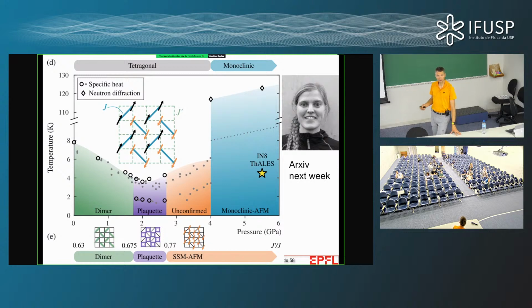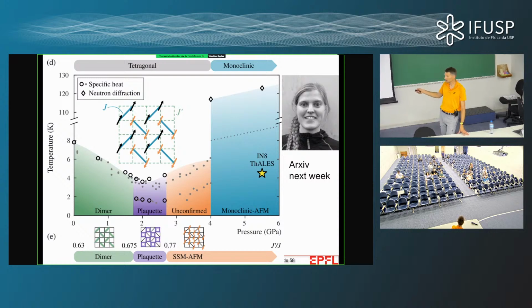Those experiments have not been successful. And so to some extent here, we have a very well-defined, so actually you can see all of this stuff happens down below 10 Kelvin. Once we break the symmetry, we actually get antiferromagnetic order at 120 Kelvin, and the J over J prime that we extract, so here, down here we have 0.6, 0.7, 0.8, and J prime over J. When we fit the spin waves here, we get 1.8.